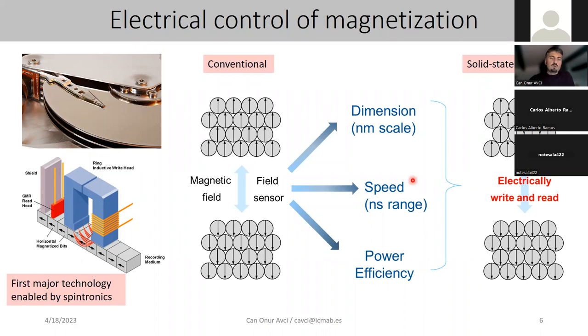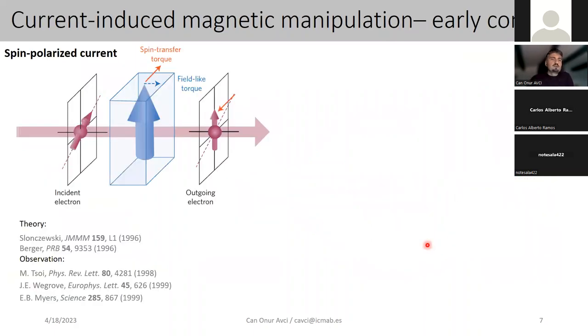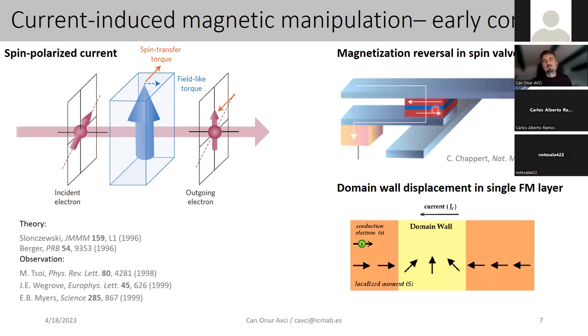Okay. So in this quest, the first major breakthrough was basically using the spin transfer torque. Spin transfer torque was predicted around the mid 1990s, around 25, 30 years ago. It is basically the torque exerted by conduction charge carriers, or electrons in this case, where the spin of each electron can transmit some torque onto the local magnetization. This concept has been used, for instance, for controlling magnetic tunnel junctions or spin valve devices, or also to displace domain walls in a single layer. And based on this concept, memory devices such as magnetic random access memory have been developed.